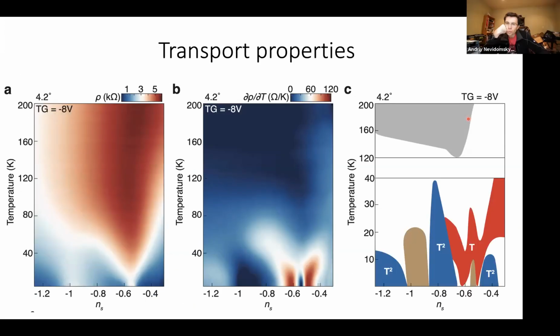What are your units of N sub S? This is in units of the Moiré filling, so 0.5 is 1/2 filling. Because there is this double band, I'm confused about the count. If you fill them completely, would you count that as 1 or as 2? If I fill it completely, it's 2 in this system. In twisted bilayer graphene it's 4 because there's an additional degeneracy, and this system is actually simpler. It's like a simple triangular lattice, and 2 electrons per Moiré site is full filling.